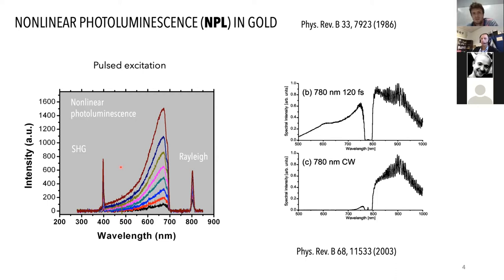Right. So usually what we do would be structure dependent, I would say. Sometimes second harmonic is a weak signal compared to the overall nonlinear photoluminescence signal. Sometimes it's predominant, but indeed what we usually do is basically cut out the second harmonic. And of course, when you do this, you will sacrifice a little bit of the PL response, because the second harmonic sits also on the photoluminescence, on the second harmonic peak.